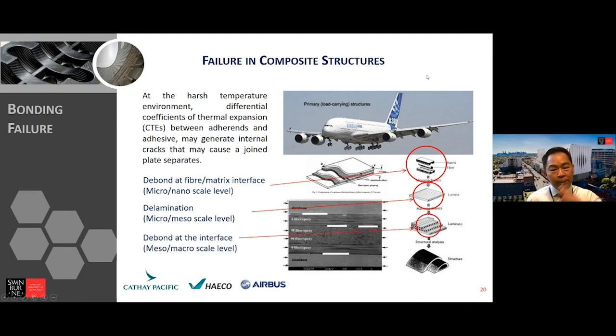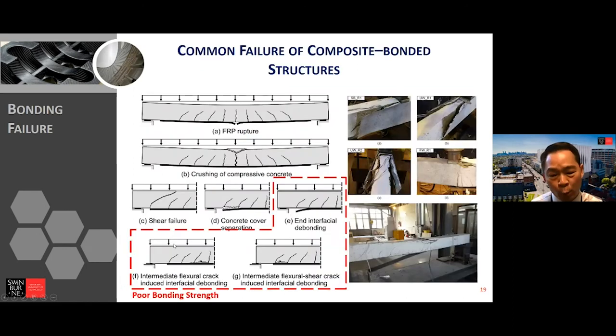If you bond a patch on the surface of the aircraft, and debond has happened, it totally affects the whole structural performance of the aircraft. So that is something we don't want to see. This one, sometimes you cannot avoid, because there's no 100% perfect composite material, no single void, but for the debond, it's basically a big problem. Debond is like this one, the whole plate debonds, and then this beam will be cracking into two pieces, breaking into two pieces immediately.